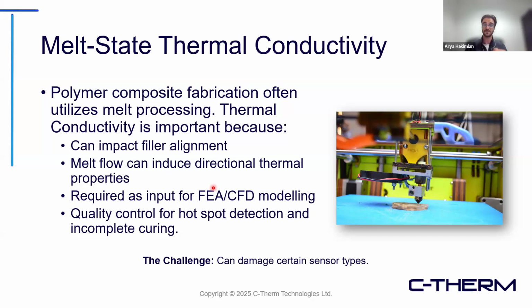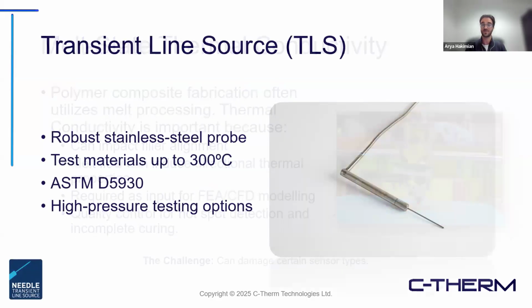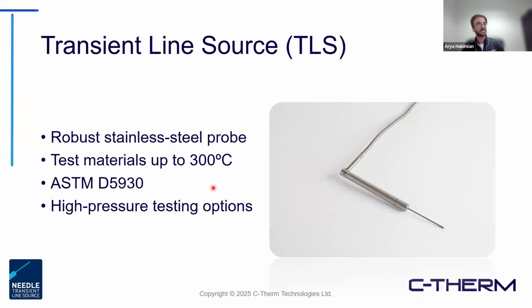So to address this type of testing, the guiding recommendation would be the use of the transient line source, or TLS. So the TLS, you can see here, is a needle probe style sensor completely sheathed in stainless steel. The ASTM standard for polymers that the TLS conforms to is D5930. We have capabilities testing up to 300 C. And one of the other aspects we didn't really talk about much for the other methods, but for the TLS in particular, there are high pressure testing options. I know with some of these injection molding systems, there's a certain temperature at which that molten polymer is held, but it's also under a pressurized environment. So one of the really important things is being able to test under a representative condition. So again, there are some nice capabilities here.